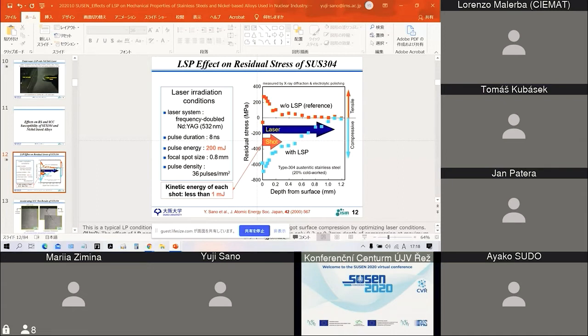That's because if you calculate the kinetic energy of each shot in the shot peening process, assuming a 1 millimeter diameter steel shot traveling at several tens of meters per second, the kinetic energy is only 1 millijoule or less. However, in the case of a laser beam, we can irradiate a laser pulse with much larger energy, so we hit the surface much harder. That's why we can induce compressive residual stress much deeper compared to shot peening. We can adjust the depth of the compression by changing the laser irradiation condition, typically the laser pulse energy.